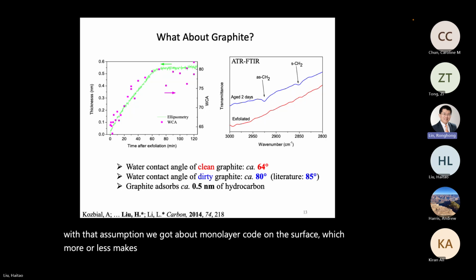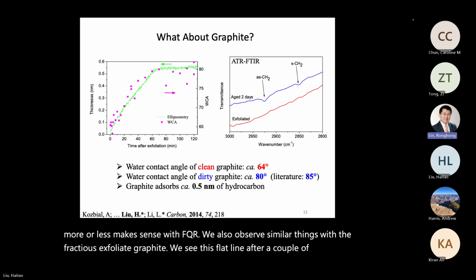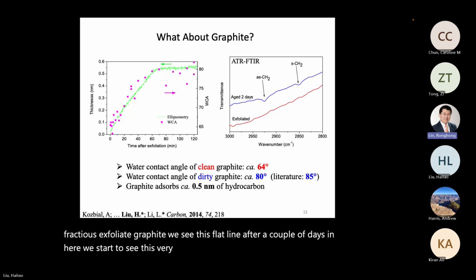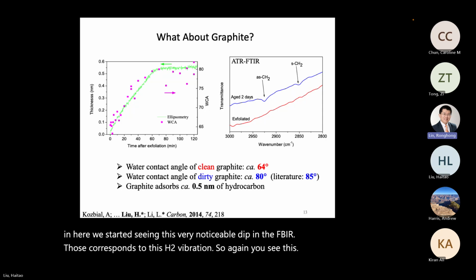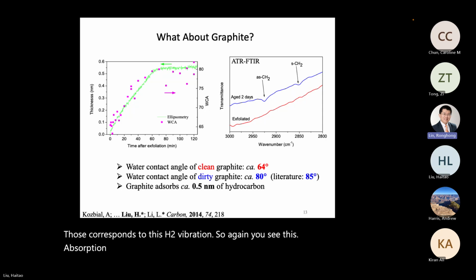Okay. With FTIR, we also observe similar things. With the freshly exfoliated graphite, we see this flat line. After a couple of days in air, we start to see this very noticeable dip in the FTIR. Those correspond to the CH2 vibration. So again, you see this surface absorption of stuff, organic stuff from air to the surface.